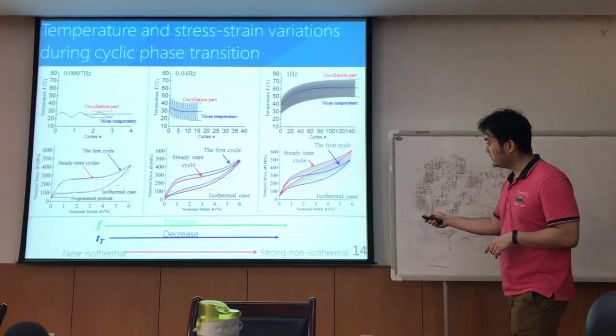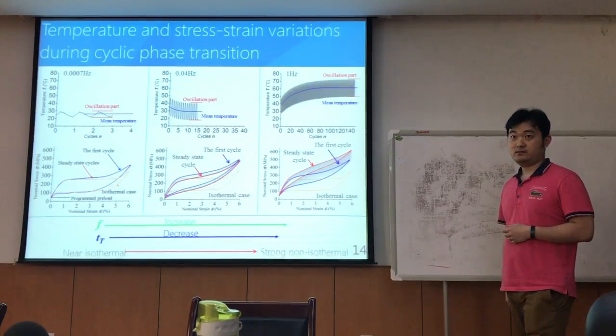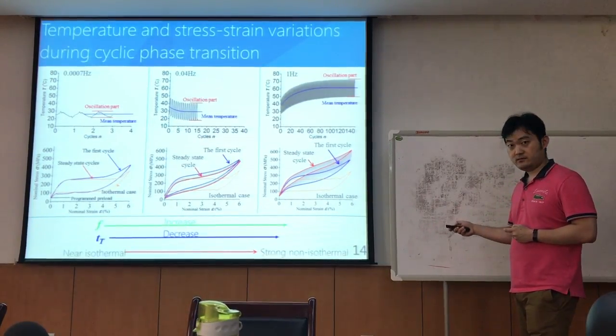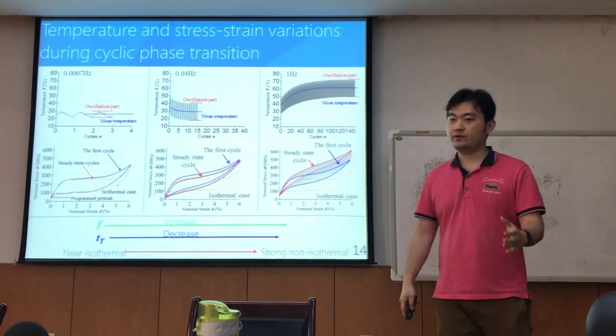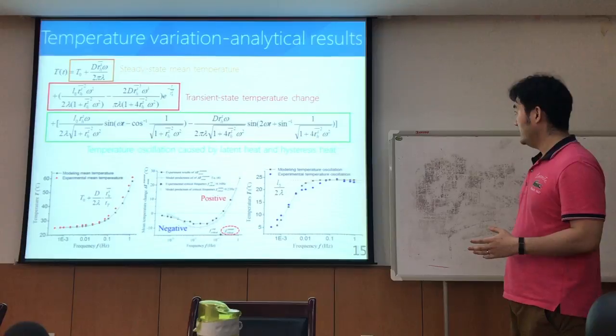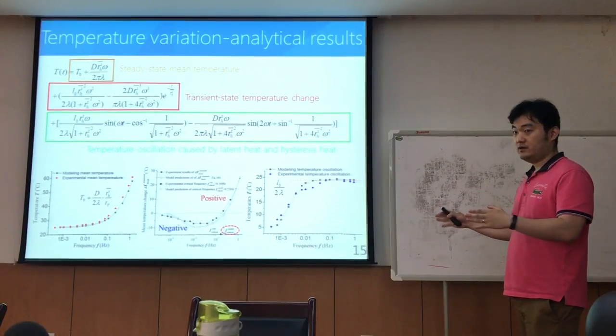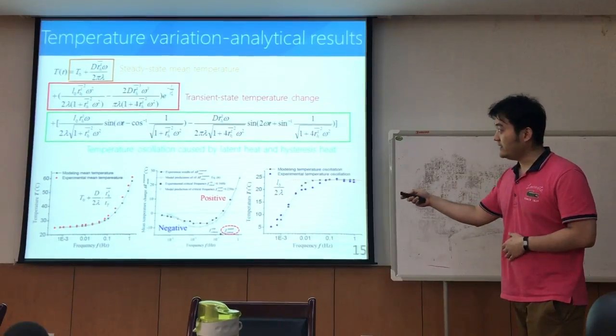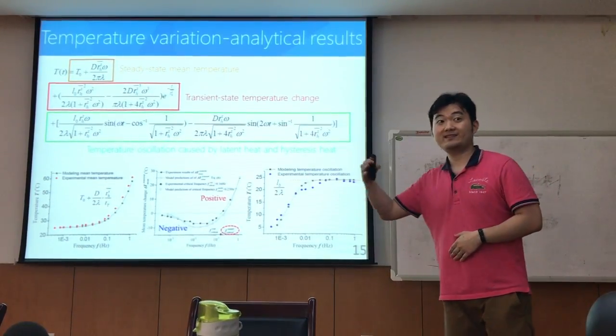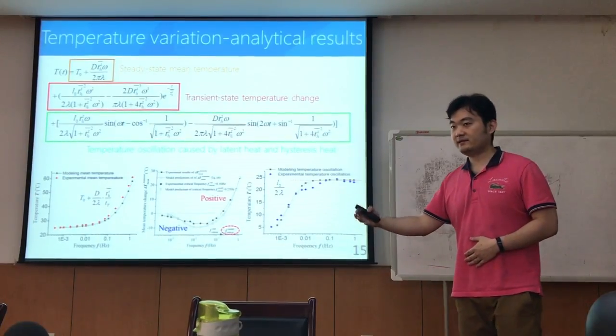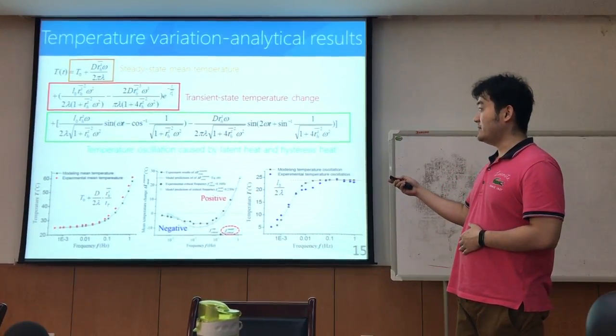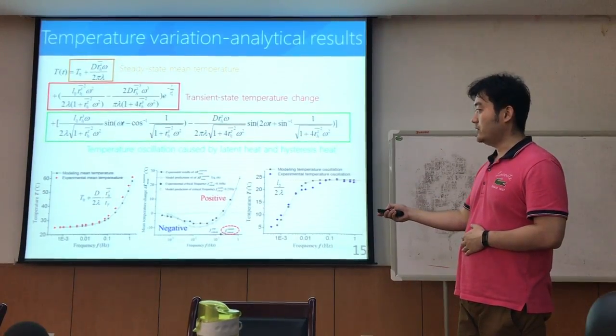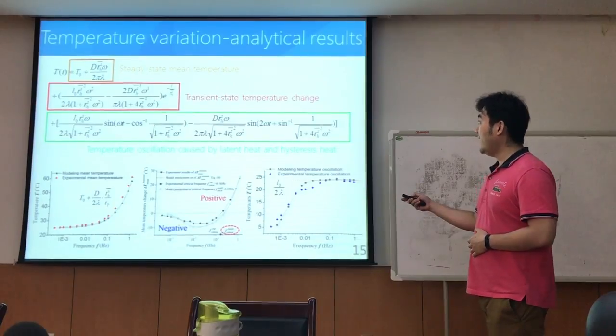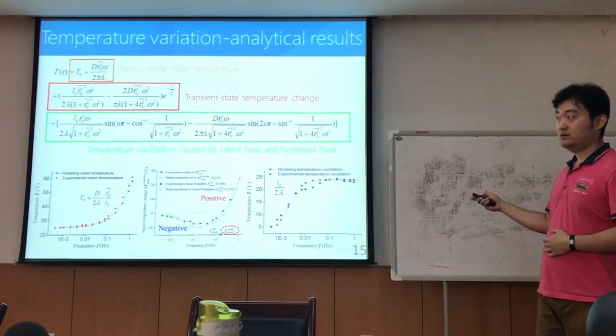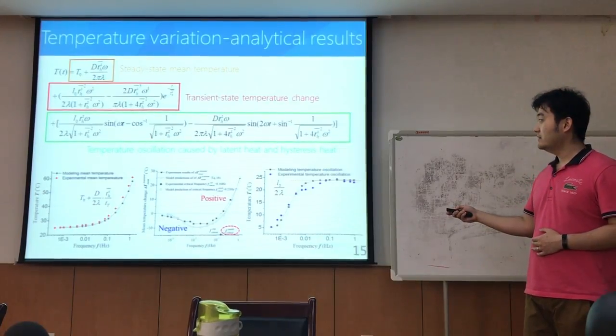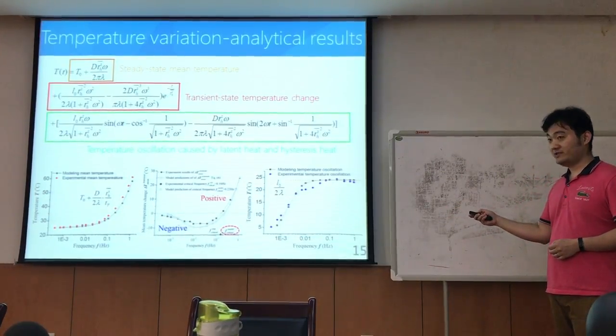Meanwhile, the stress-strain curves will shift up. Okay, they are correlated, but how? We build our own model. And we find that with these analytical results, the temperature variation during the cyclic loading can be represented as the superposition of the steady-state mean temperature, which changes monotonically with the loading frequency, and the transient state temperature change, plus the temperature oscillation caused by latent heat and hysteresis heat.